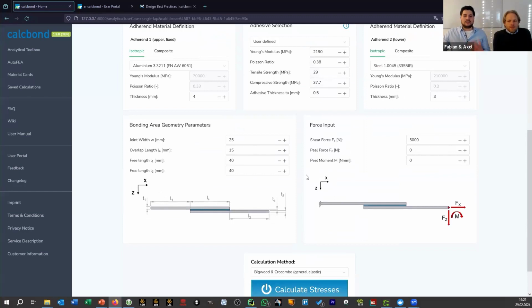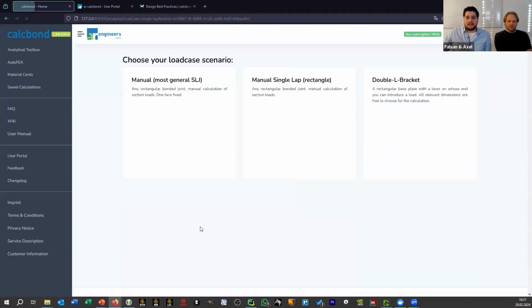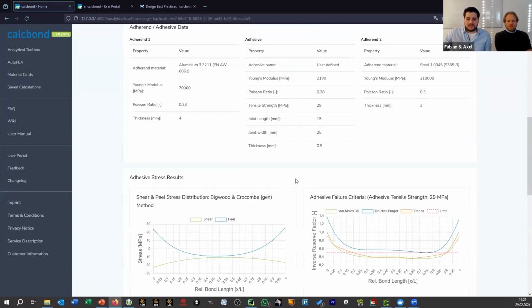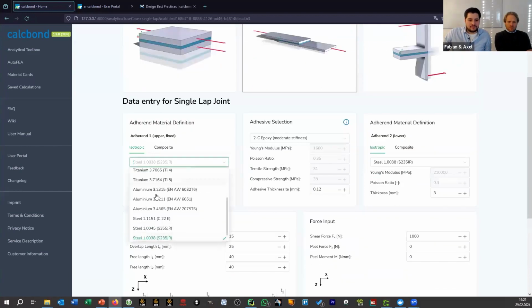Yes. So we have the steel alloy as the adherent material on the right with 3 millimeters thickness, and we have 4 millimeter thickness on the left with aluminum. So we have an asymmetrical joint configuration, and I'm keeping the forces as they were. And if I calculate again now, I can see a slight asymmetrical distribution of the stresses. Maybe I can give it even a little bigger push just to make it more clear.